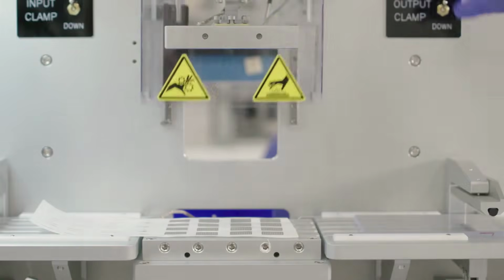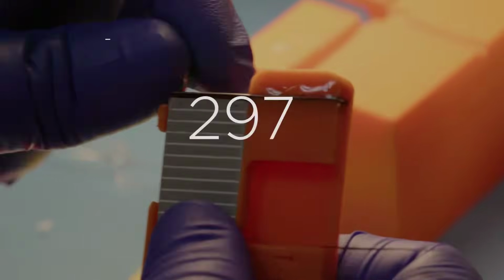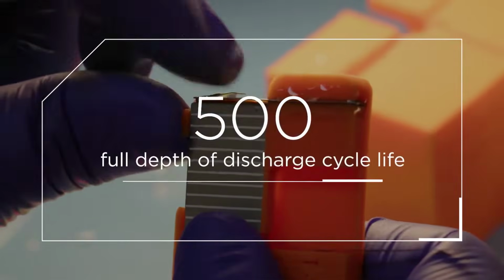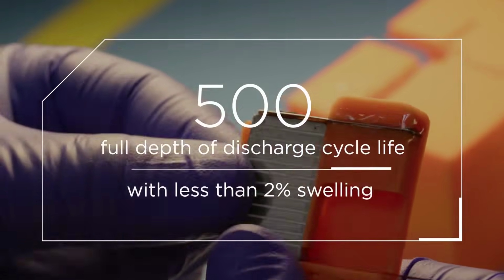To solve silicon's poor formation efficiency, where up to 40 to 50% of lithium can be trapped during first charge, Enovix adds a pre-lithiation step. A thin internal lithium source replenishes lost lithium and provides a reserve to support long-term cycling. Short diffusion distances in Enovix cells allow this process to complete in hours rather than weeks.